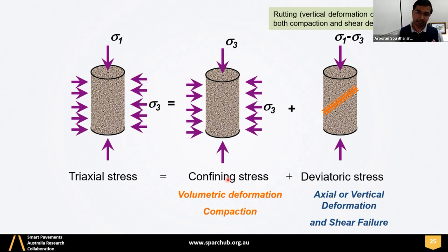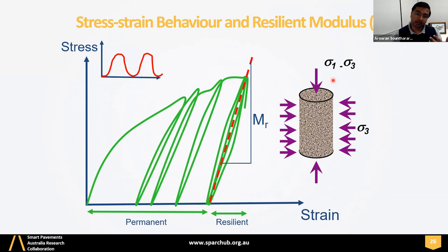So what happens here is the sample experiences deformation mainly in two ways. One is a volumetric deformation due to this confinement, which is also a compaction in the material itself. And then axial vertical deformation. So why does this axial vertical deformation happen? Because you are applying the deviatoric stress, which causes the vertical deformation. And at some stage, the soil or the sample will fail, right? That's called shear failure. This is a 1D element test, which captures the essential behavior of this material under cyclic loading in the field, right? Then under cyclic loading in the triaxial, how this material behaves is illustrated in this figure.